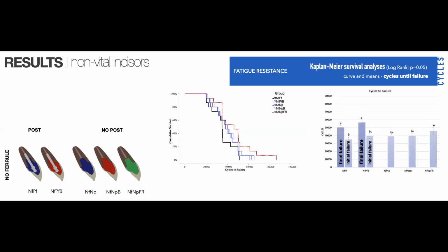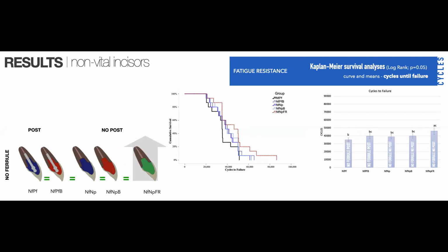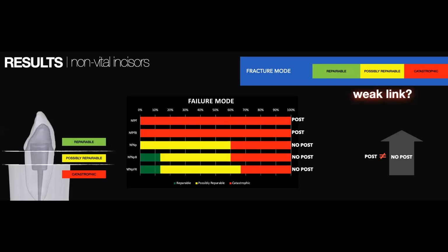when we make the comparison with final failure, everything here is the same, okay? If I'm doing with post and without post, it's the same. But when I use fiber reinforced composite resin, I have a better result, as you can see here. But that's only for the amount of cycles of survival. When I look at the failure mode, what you see in red is catastrophic failure. And when we place a post, 100% of the failures were catastrophic, okay?